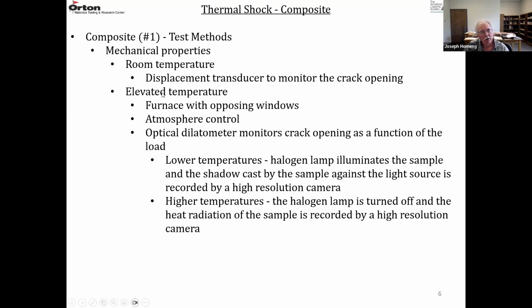So in this work, for the elevated temperature test, the wedge sample is put in a furnace. On opposite faces of this furnace, there are high temperature windows, most likely a fused silica material that's transparent or a sapphire single crystal alumina that's transparent. You have to control the atmosphere, so it has to be a non-oxidizing atmosphere like nitrogen or argon. You don't want to oxidize the carbon.